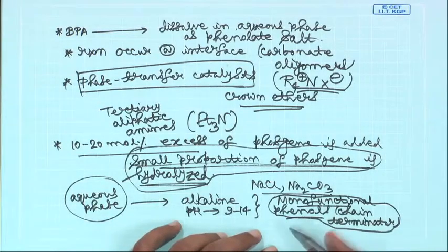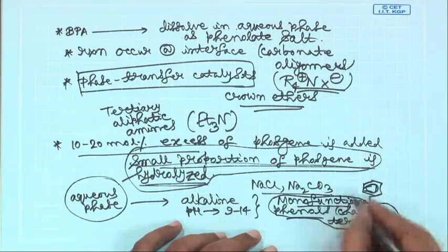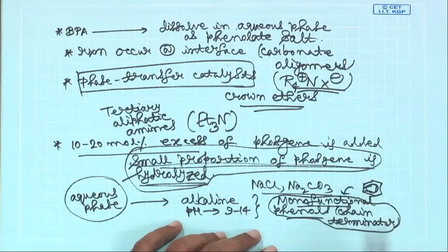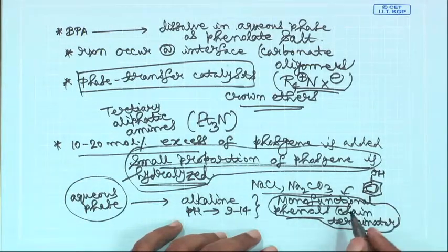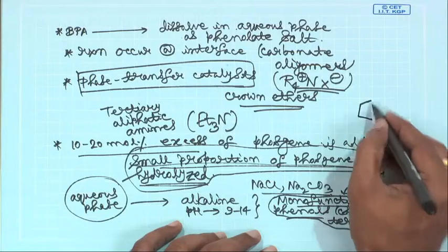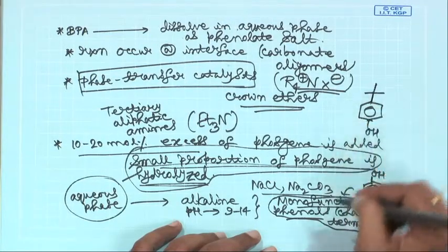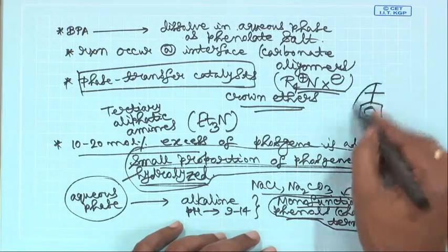So, these monofunctional phenols, what could be the compound that you are using? I mean, this class of phenols you are using. You can use phenol itself, or you could use say 4-tert-butyl phenol. So, those kinds of monofunctional molecules you could use to control the molecular weight.